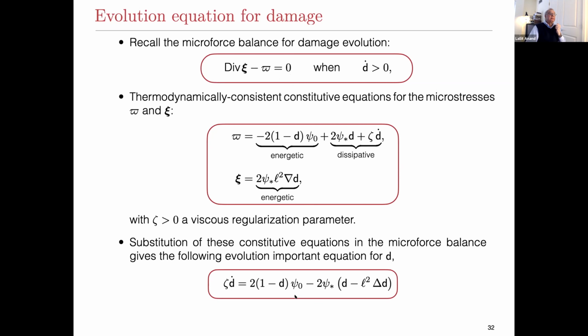Okay. And this is the so-called phase field model. Here I'm doing it purely as a gradient damage theory. The phase field essentially is when D is equal to 0, it's the intact phase. When D is equal to 1, it's a failed phase. But there are no double well potentials or any of those other things. This is trying to describe a dissipative phenomenon, not an energetic phenomenon. Of course, the damage is driven by the elastic energy and some other terms, but unlike in regular phase field ideas in material science, there are no double well potentials or the like.